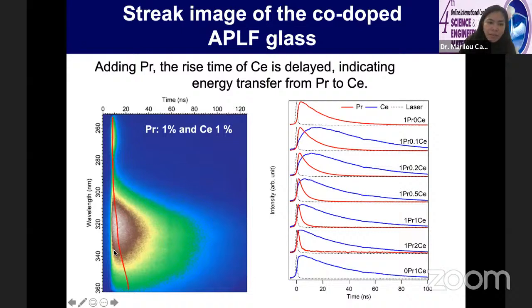This is the streak camera image showing the emission from praseodymium and emission from cerium. We can see that for purely cerium-doped glass, we have this decay time. But if we increase the concentration of praseodymium, we see a delay in the rise time of cerium, which confirms the energy transfer from praseodymium to cerium.